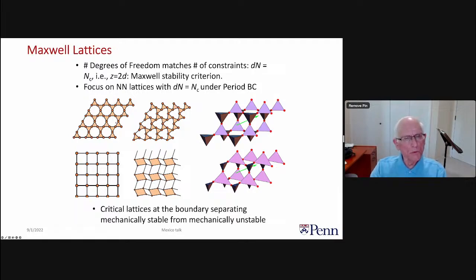So here we have structures where each site has 4 neighbors, and each site has 2 degrees of freedom, and each bond is 1 constraint. So you can see that if we have, on average, 2 bonds per site, which is what you have if the number of neighbors is twice the dimensionality, then under periodic boundary conditions, at least, all of these lattices fall into the Maxwell lattice category. That's my definition of the Maxwell lattice. So the simplest one, of course, is the square lattice. You can shear the square lattice and you can distort it in a manner like this. And each of these operations leads to a different phonon spectrum and different surface modes in particular.